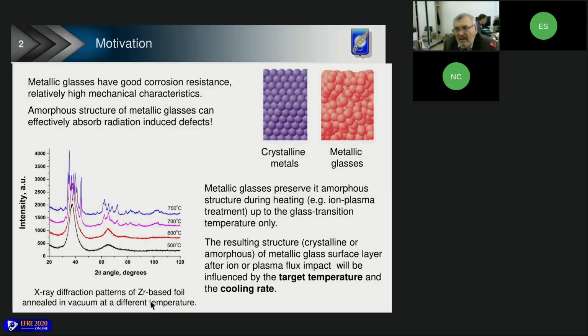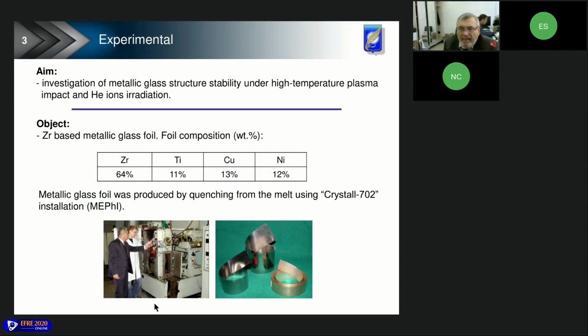So, investigation of metallic glass structure stability under high-temperature plasma impact and helium ion irradiation were the main aims of this work. The samples of zirconium-based metallic glass, in the form of foil, were produced by quenching from the melt using this type of installation, located and developed in MEPhI, Moscow. Here you can see that two isomorphous elements, zirconium and titanium, form the elemental and structural basis of the foil. The approximate thickness of the foil was 50 micrometers.